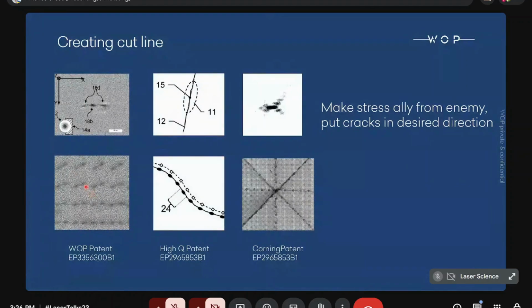You can see that if the modifications are deviating from your desired cutting line, as in the previous direction, they are not joined. When you direct them in the same direction, you have a cutting line. And this should be quite precise, because this deviation is roughly 10 degrees, and you can see that the cracks do not join.